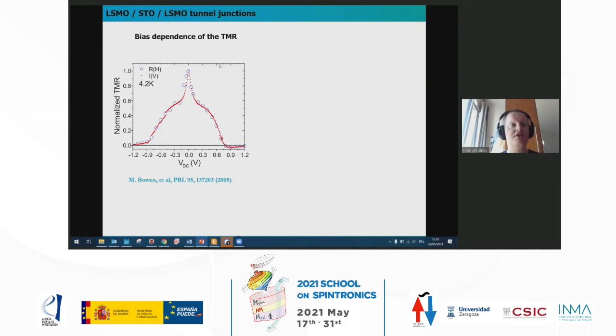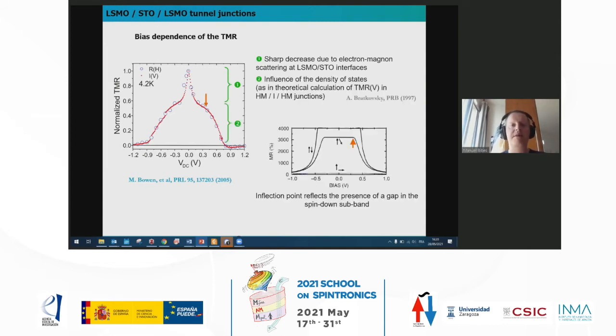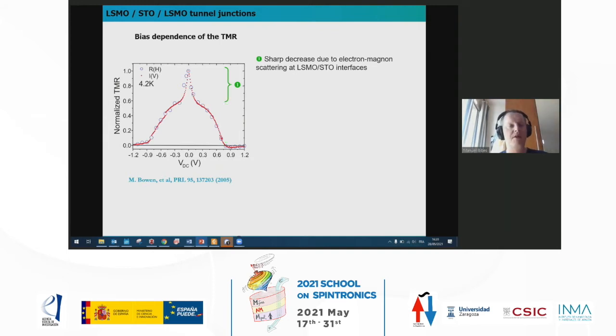And just in these symmetric tunnel junctions, LSMO, STO, LSMO, if you measure the TMR as a function of the bias voltage that you apply between the first and the second electrode, basically, as you do that, you are sending fully spin polarized electrons into the band structure of the second electrode at a given energy that corresponds to this bias voltage that you apply. And so in principle, if you remember, you have a band gap in the minority states for these half metals. So in principle, as long as your electrons arrive at an energy lower than the bottom of the conduction band for minority spins, basically in the minority band gap, you have a fully spin polarized current, and you basically should observe an infinite TMR.